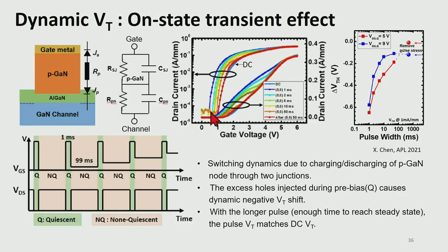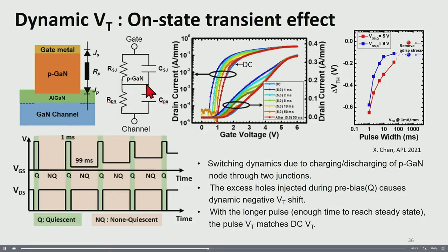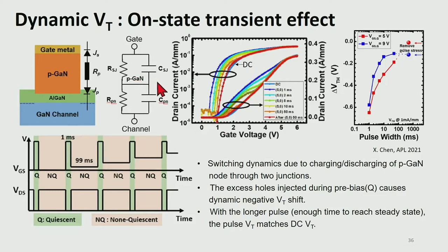For example, if you do the transfer curve sweep with a very short pulse, the initial P-GaN potential can be affected by the pre-sweep condition. So if you see this bottom left figure, before the sweep, the positive gate pulse stress was applied. And the excessive holes accumulated in the P-GaN during this positive gate voltage stress affect the P-GaN potential and cause the early device turn on.